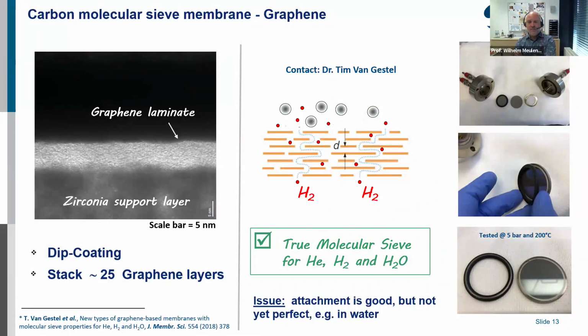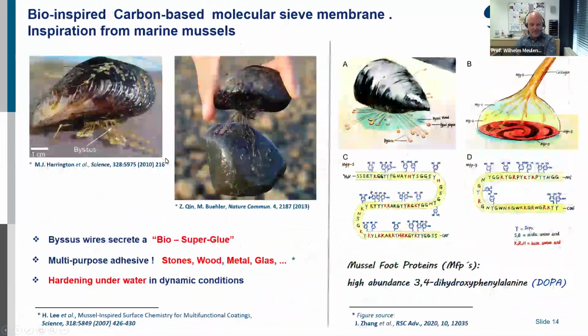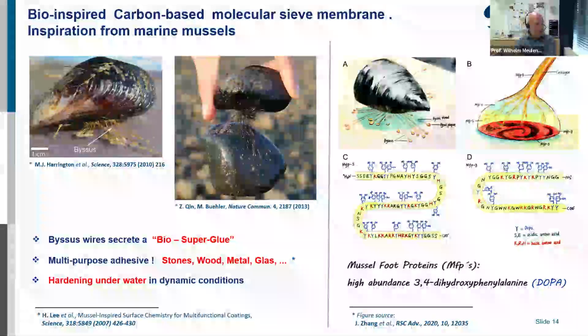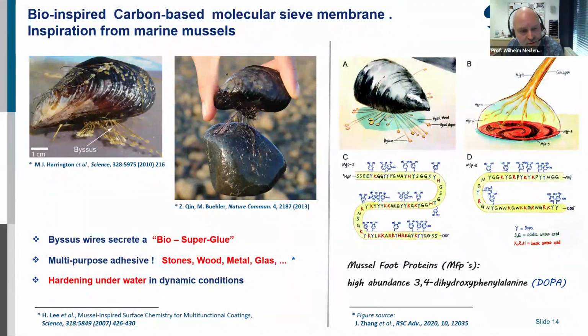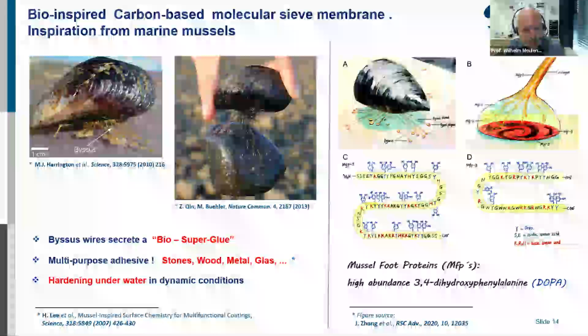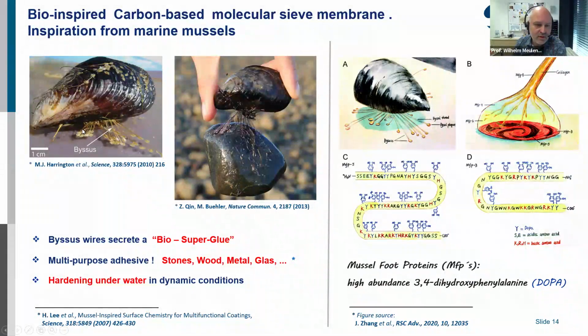And then my colleague, Tim van Gestel, was thinking about how to increase this attachment of the membrane to my support layer, which is here the intermediate layer, zirconia with 5 nanometer pore size. And here you see the graphene laminate. One idea he picked up from literature from our colleagues at MIT. These colleagues were focused on making glues. They looked to nature, to mussels, and the question was how a mussel attaches to a stone, and you also see underwater that this attachment is very strong.